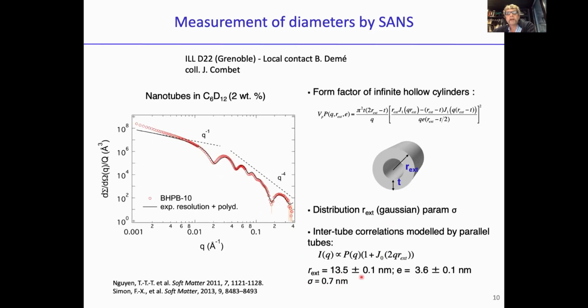So here are the parameters that we can deduce from this fit. So the outer diameter is about 27 nanometers. And you can see why we use this technique, because it's very accurate. The accuracy is about 1 angstrom. Finally, the only remaining discrepancy between the theoretical and the experimental curve is because we have correlation between tubes, because they are not isotropic. They form bunches or bundles of nanotubes that can also be modeled. So this is how we can measure all the parameters on these nanotubes.